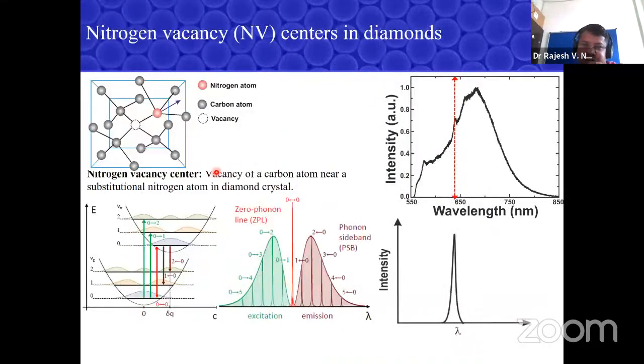So again, more technically, if you have nitrogen vacancy centers, these samples can either come in nanoscale, like nano diamonds, particles of 150 nanometer in diameter. And you can also grow it like a thin film, like CVD grown diamonds. You can grow the diamond in the laboratory and create these defects in it. And if you measure the PL spectra or the spontaneous emission as a function of wavelength, you can see it is a very uninteresting broad emission. Okay, but what the community wants, what we look for, is to have a spectra just like this. This is a cartoon picture which I made.